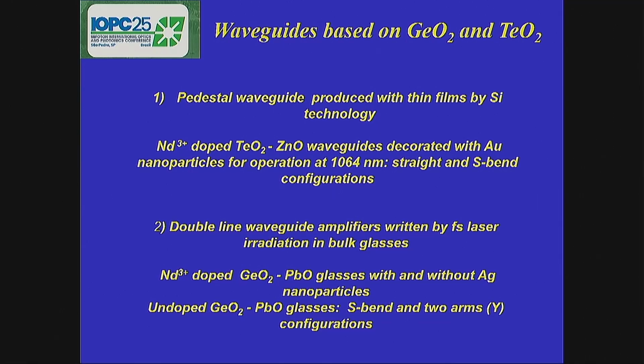For the case of the femtosecond irradiation, we use glasses with 2 millimeter thickness, and the waveguides are inscribed directly in the glass. In the other case, the thin films are of about 500 nanometers. I'm going to show you results that were already reported. In this case, 2 results of passive waveguides, and in the other case, 1 passive waveguide and 1 undoped glass, or a passive waveguide.